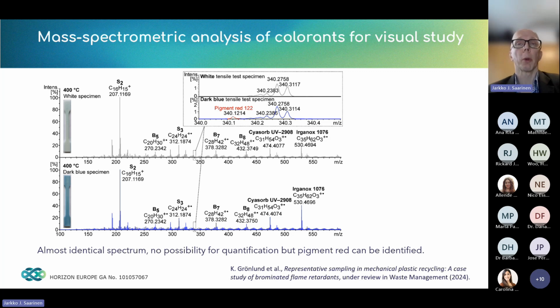quantified analysis. However, we also wanted to test whether we can see the colorants that have been used in the visual study. And indeed, we pinpointed two different pigment components from the blue component, which was used as a colorant. And then indeed, we can see the pigment red component as shown here on the magnified image, very small peak in the spectrum, but still visible in the mass spectrometric analytics, showing first the accuracy of the mass spectrometric tools that we have in use, but also at the same time we can see that since the intensity of these pigment peaks is very weak, they are not suitable for the quantification of these materials. So for that reason, we move on towards the brominated compounds.